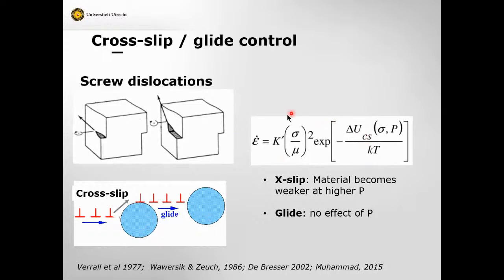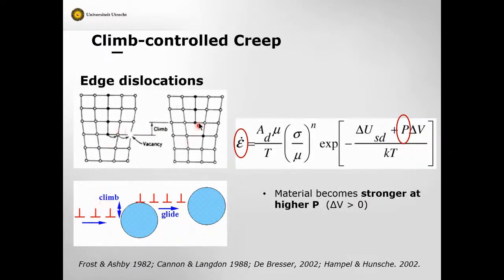And this is the result that you get for this type of process, and you see an exponential dependence on stress here. So it is much, much more stress sensitive. If you express this as a power law, you typically get a power law fit with an n value of something like 7, 8, or 9. And interestingly, this is also dependent on pressure, but the material becomes weaker with increasing pressure, or there's no effect. Whereas if this climb process is involved, a different microphysical mechanism, the material becomes stronger at higher pressures.